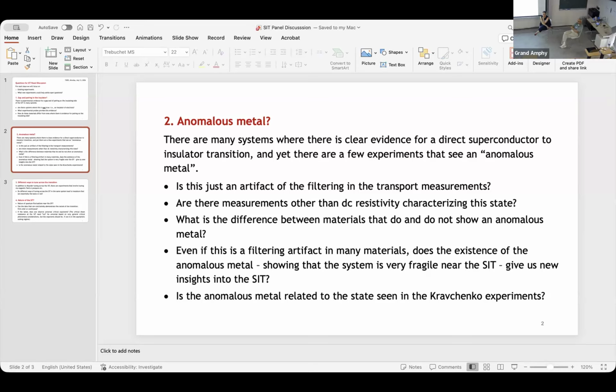One comment: we actually studied the zero Hall resistance, and simultaneously we can see h over 2e quantum oscillations for such an anomalous metal state. Then it looks like the Cooper pair dominates this state. In which material? YBCO, the iron-based superconductor, the nickel superconductor and others. I don't know if Ding has done something in other systems, but in our systems there are three kinds of high-Tc crystal thin films.